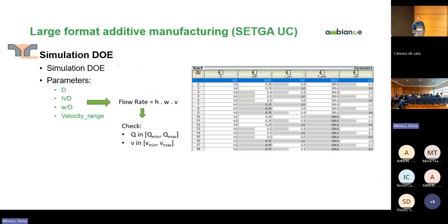Also, we cover the velocity ranges that we can afford. That means that in the end, if we define the height and the width and the velocity, we need a flow rate. But this flow rate needs to be between certain limits. The limits are the limits of the extruder. And also the velocity is controlled and is imposed in several limits. So for this combination of parameters, we check the flow rate and we keep the limits to be inside the extruder limits in terms of flow rate and for the ranges of the velocities. That means that we are covering all this suitable range for the velocity.